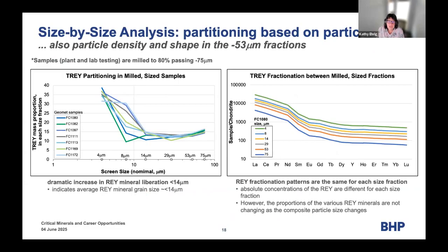The things that are interesting, so even when we don't have access to full detailed mineralogy, we're very privileged to do that. What I learned from a metallurgist 30 odd years ago is that sizing assays on a size by size basis, if you know what's going on with the mineralogy, actually reveal quite a lot. And in our deposit, it certainly does. So what we're looking at on the left-hand side, log scale, and nominally just a screen size, and those just represent a bunch of future ore characteristic samples, and just looking at what the mass proportion, the recovery is for each of the size fractions.